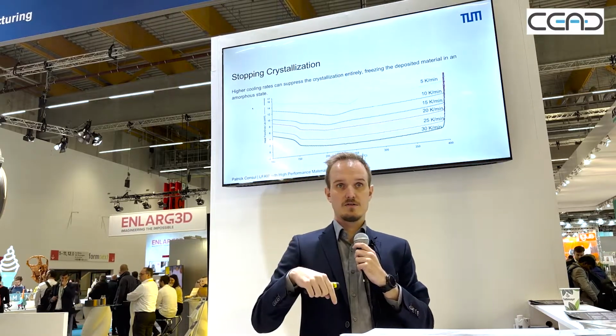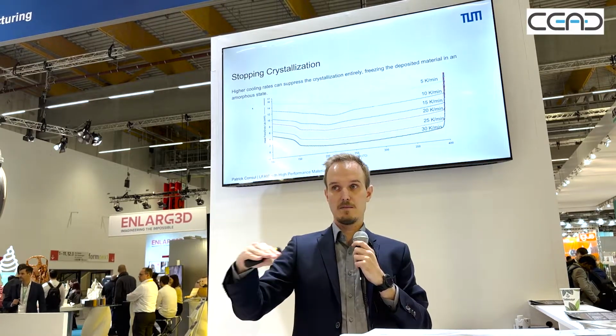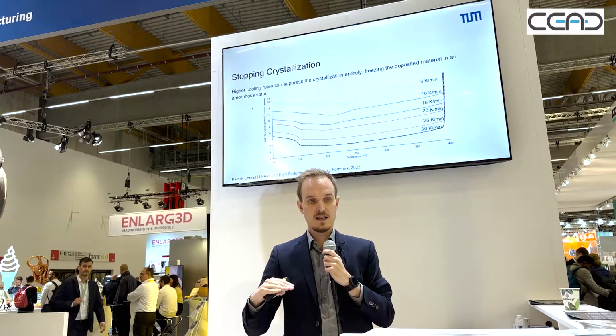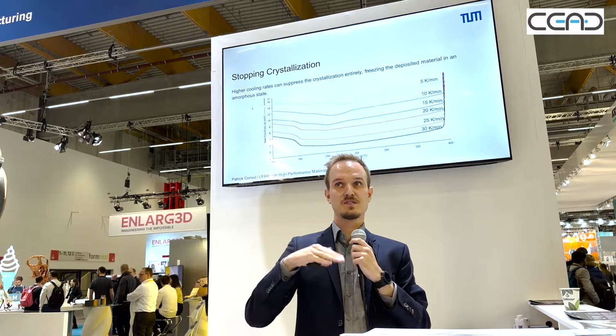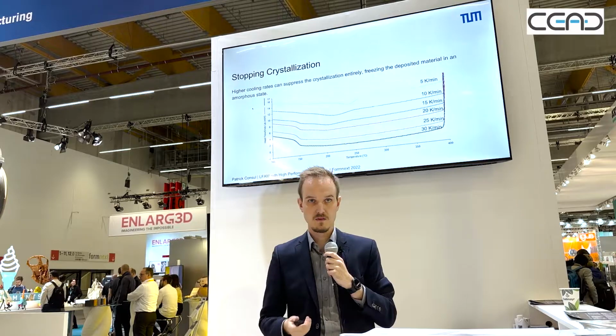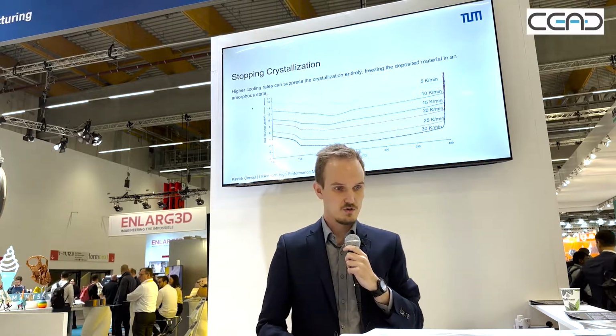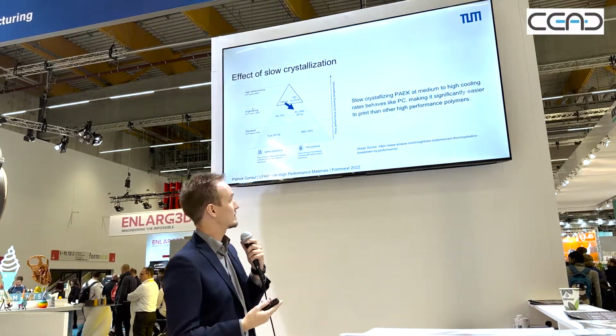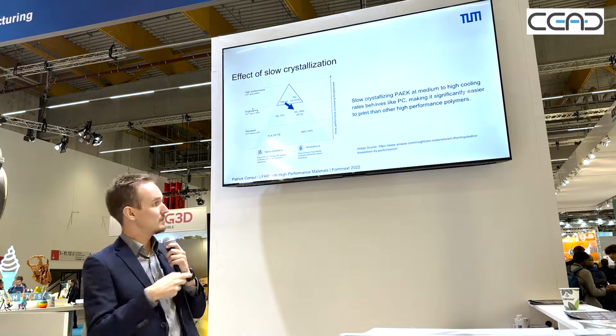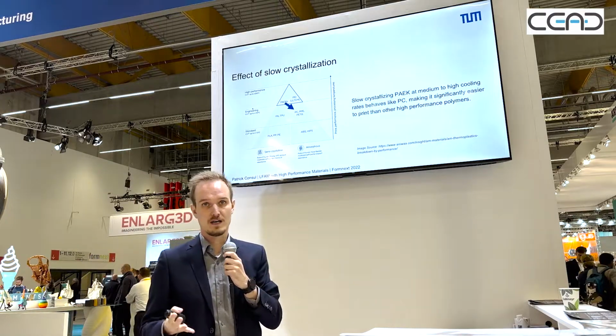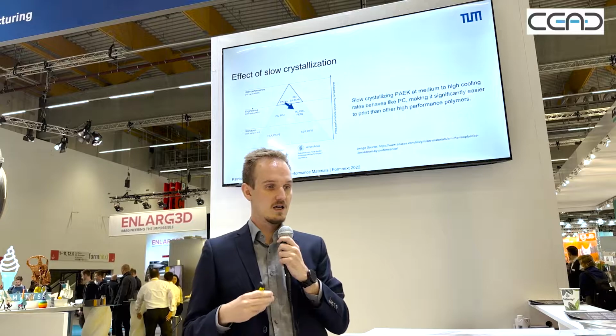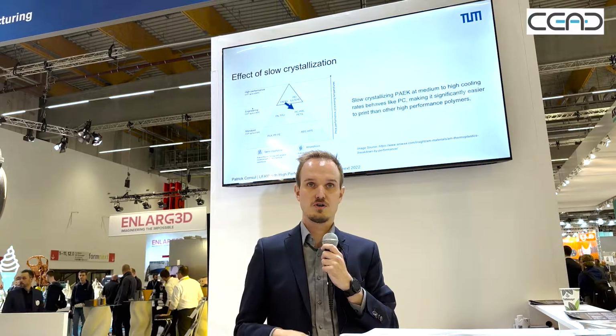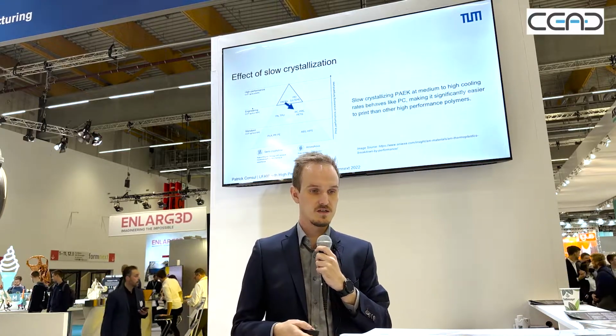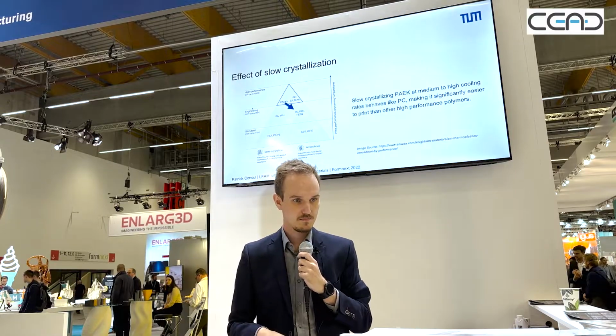And when the next layer is deposited on top, you again apply heat. You can still bond the layers together, and then the residual heat will crystallize the layer below. That's the idea behind it. So hopefully, if everything works, it should make the PAEK behave more like a polycarbonate, which also has a glass transition temperature at about 150 degrees Celsius, like this PAEK.